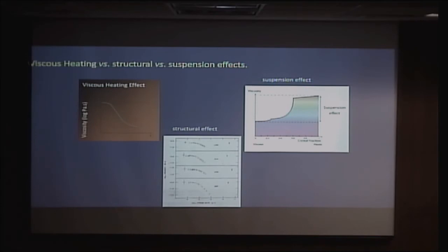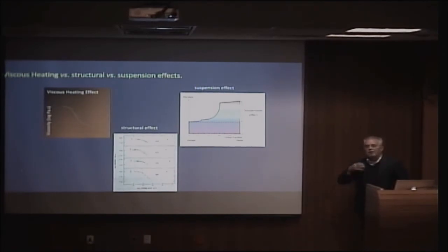And once you got that figured out, once you got that calibrated, you have a third effect. You have this structural effect of the liquids. If we push these liquids into the yellow zone, they start to behave no longer as liquids. They start to lose their liquid character. They start to behave with rigidity. And rigidity is a problem because it's an elasticity. It means you're storing the energy somewhere. You're not dissipating it. Well, if you're storing the energy somewhere and you keep pushing, sooner or later you're going to have a problem because that energy is all still in the system somewhere. And that's basically what leads to the explosion.